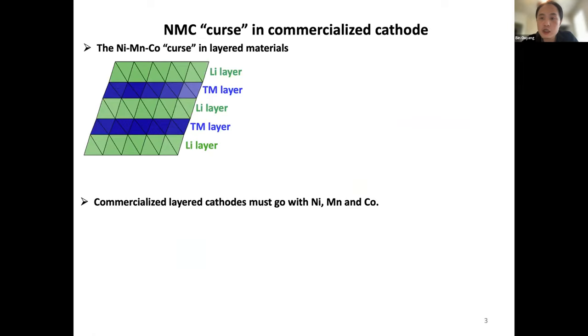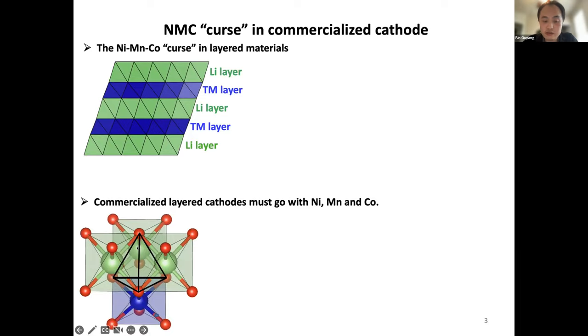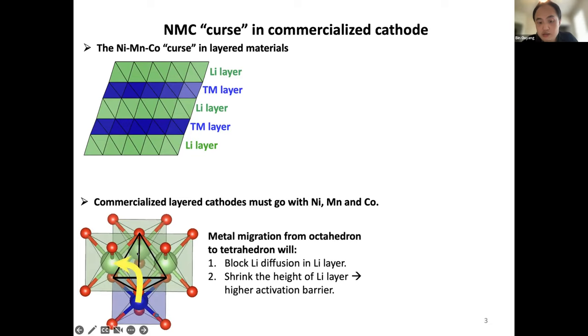NMC stands for nickel, manganese, and cobalt — the three main metals we can put into a battery. The reason behind it is that when you remove lithium during battery use, you leave an empty lithium layer, and there's a tendency for the transition metal to migrate from the octahedral site through a tetrahedral interstitial into the lithium layer. This migration is detrimental: it blocks lithium diffusion and because transition metals are typically smaller, they shrink the lithium layer height, causing lithium to diffuse much slower.